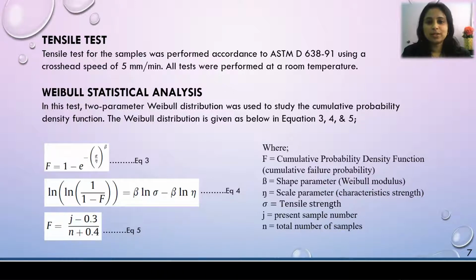Equation 3 shows the cumulative probability density function, also known as the cumulative failure probability, which is F equals 1 minus exponential of negative (tensile strength divided by scale parameter) to the power of shape parameter, or Weibull modulus. This function is then further derived by taking the natural log on both sides, which results in equation 4, which is ln ln (1 divided by 1 minus F) equals Weibull modulus times ln strength minus Weibull modulus times ln scale parameter.